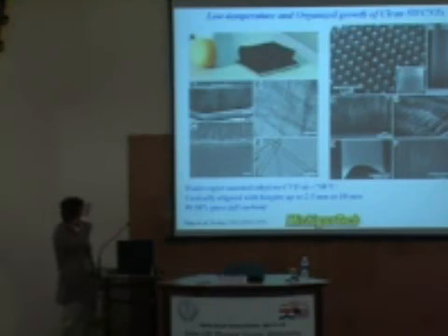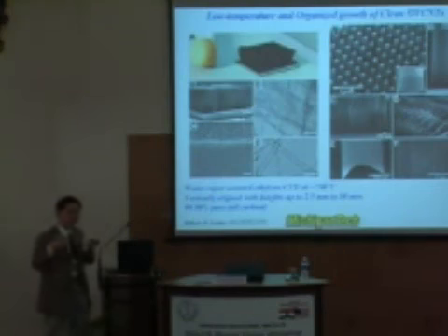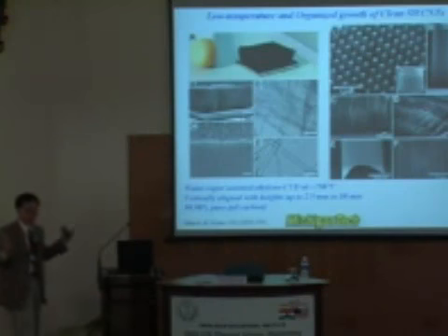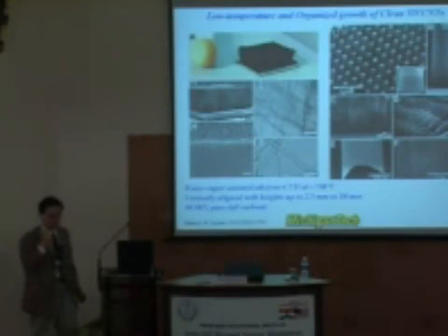And this is a very important work in the sense that they're using water to clean up the catalyst and clean up some of the amorphous carbon so that the tube is nice, clean, and pure. However, if you think carefully, if you're using water to clean the amorphous carbon, there is a chance that you will oxidize your carbon nanotubes at the same time. So you will create defects in your tubes. So this is very exciting work, but it's not the best.